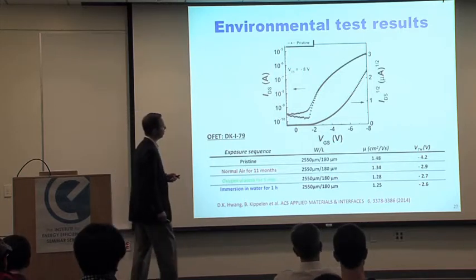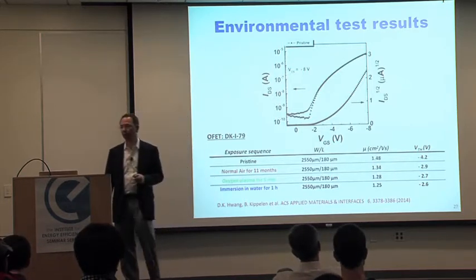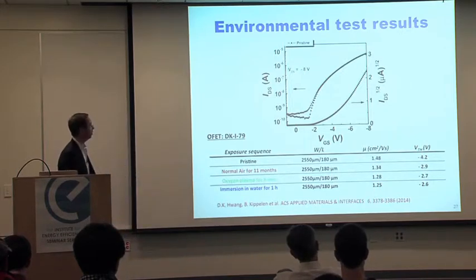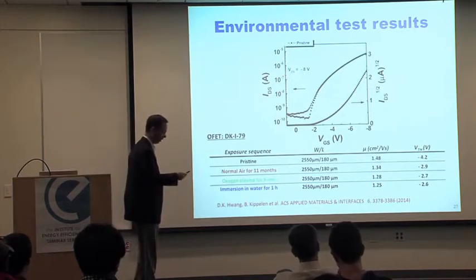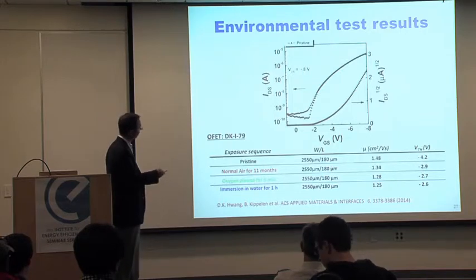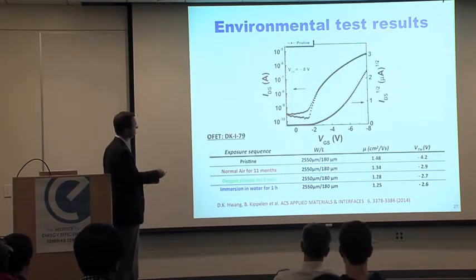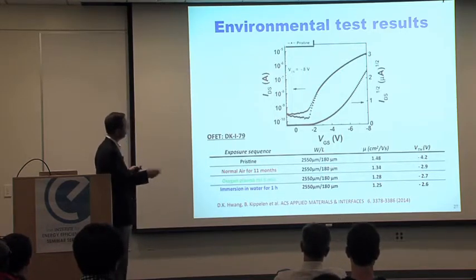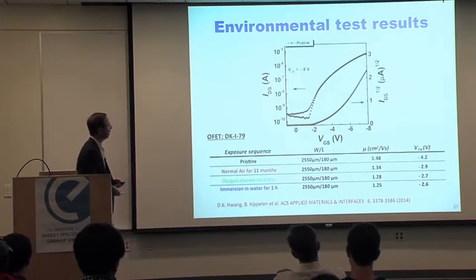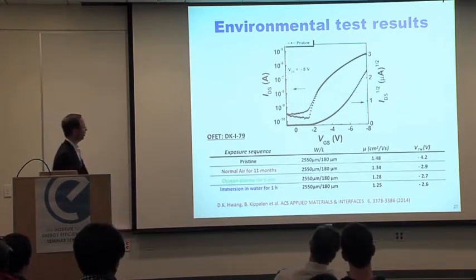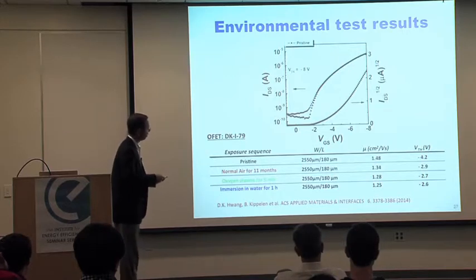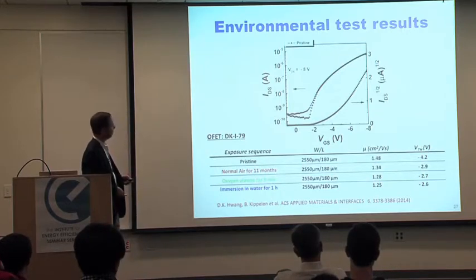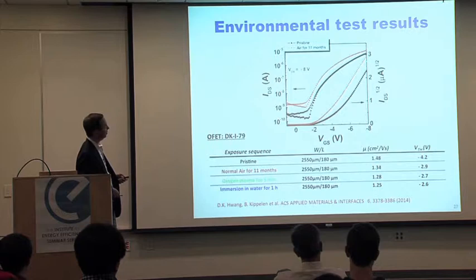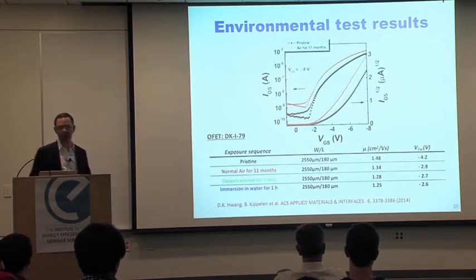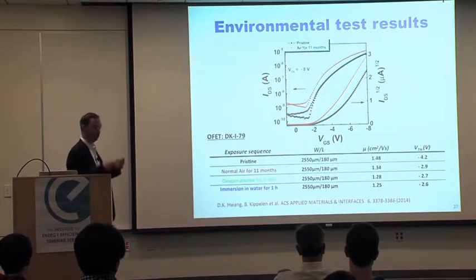So just to show you in more detail what these different processing conditions do to the transistor, that's a transfer characteristic of a transistor right after fabrication. The device has never been exposed to air. And I apologize here, when he did this, these are pretty ugly transfer curves with a lot of contact resistance. We have now transistors with very clean transfer curves, but here it was just for the purpose of stability. So if you take these devices and leave them in air for some time, you see changes in the transfer characteristic, but it stabilizes.